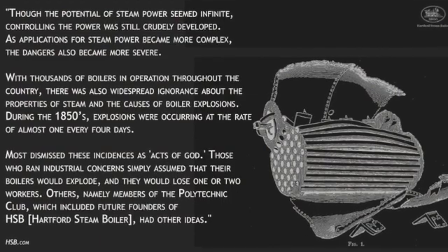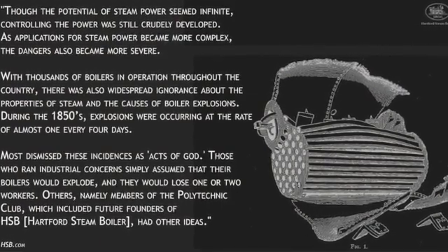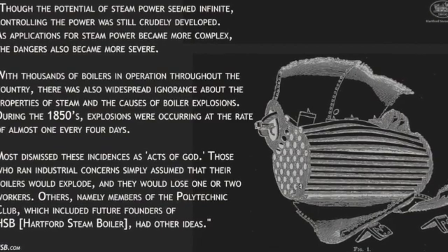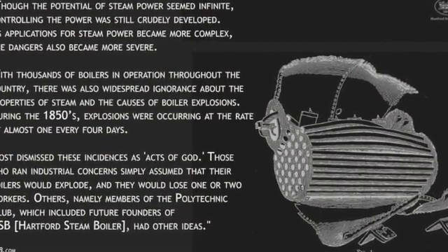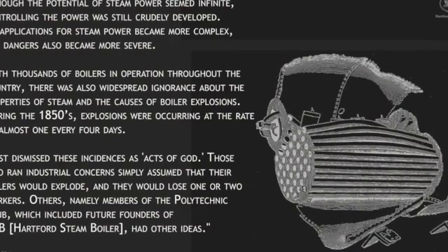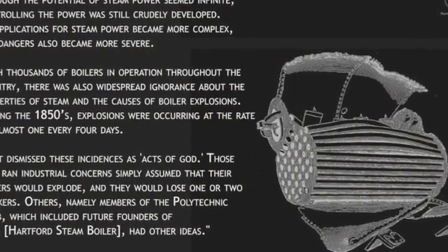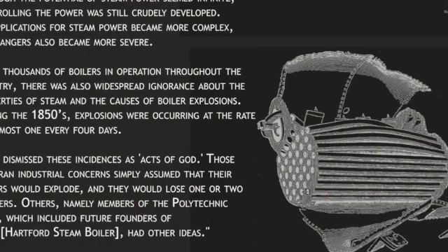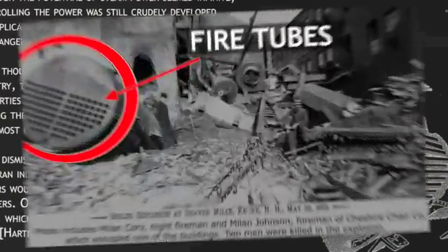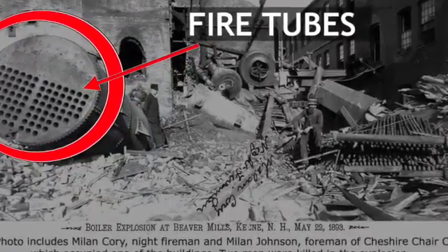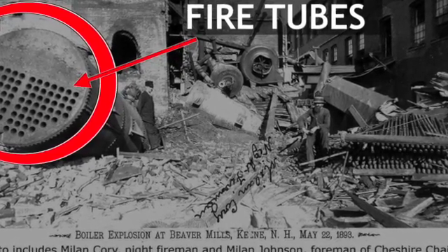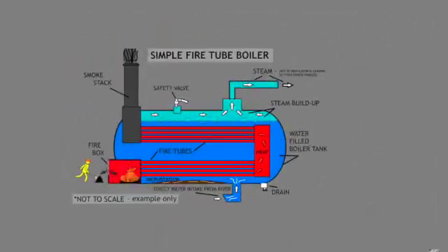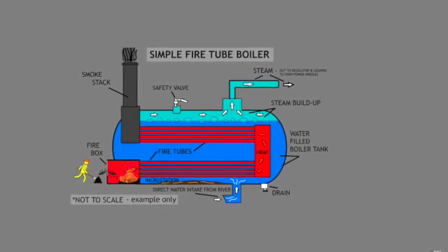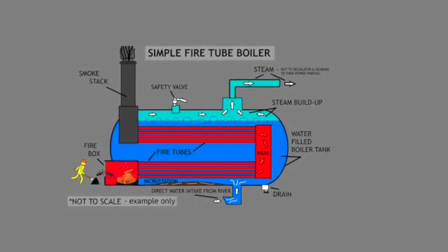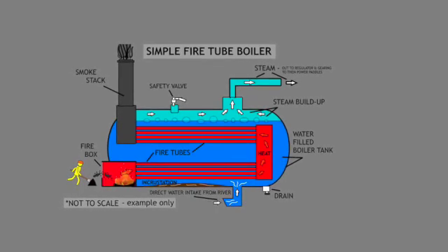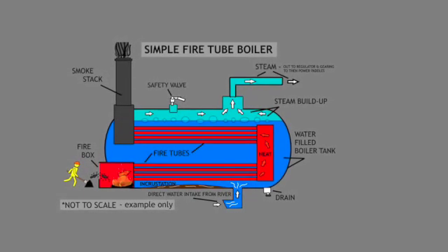This constantly superheated and cooled the material into brittleness, likely causing the temporarily repaired boiler to be unable to withstand the pressure, explosively failing into destruction. The second factor to take into account is the use of sediment-ridden river water to be turned into steam. The sediment within the water would clog between the flues rather easily, increasing the pressure artificially. This sediment would also sink to the bottom of the boiler, creating hot spots which would embrittle the material.